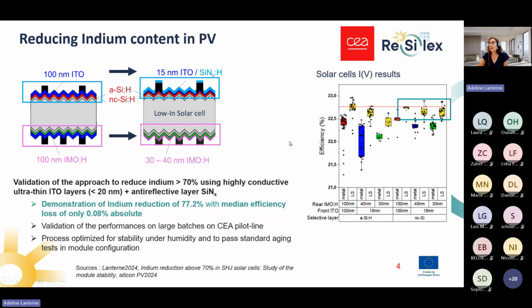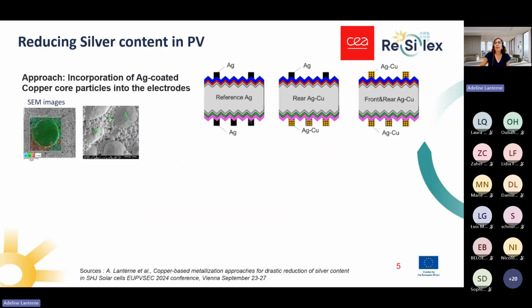So that was one important result here. And if I now continue on silver reduction for solar cells, in the project we also work on several approaches. The one I'm presenting here is also the one where we reach high TRL, like TRL 7, I think. Here, the approach is to incorporate silver-coated copper core particles into the electrode. Usually the electrode is made only of silver, and here we have silver and copper inside it. We apply this either on the rear side of the cells or on both sides.